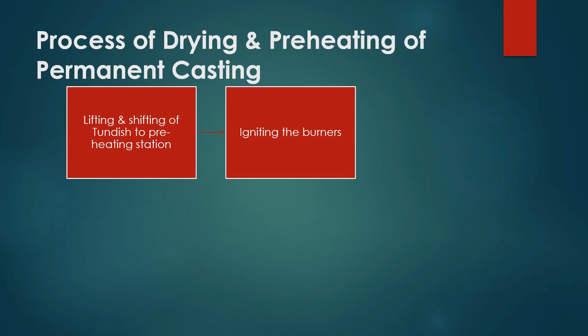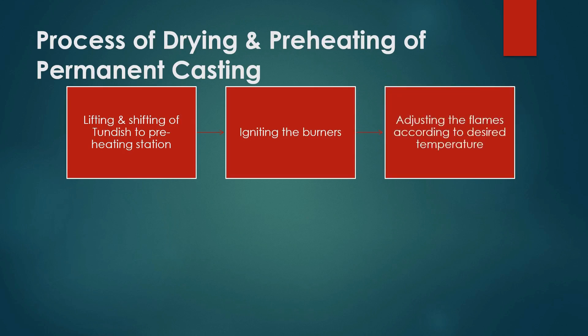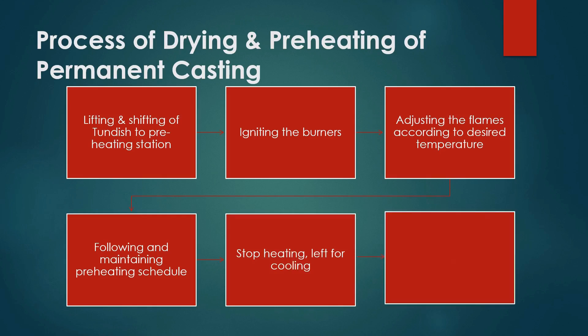After 24 hours, the former is removed from the tundish, and it is ideal to leave the casting wall for another 24 hours in open air for further air curing. Then the final step is firing of the castable lining. For better bonding and strengthening of the castable lining, it is heated over 72 hours depending on the thickness of the casting wall. Please see the process flowchart and heating schedule.